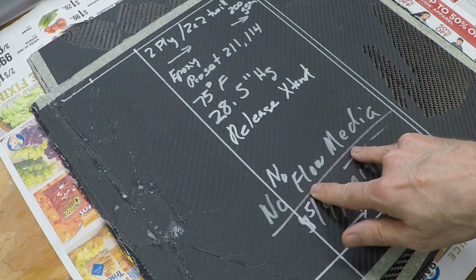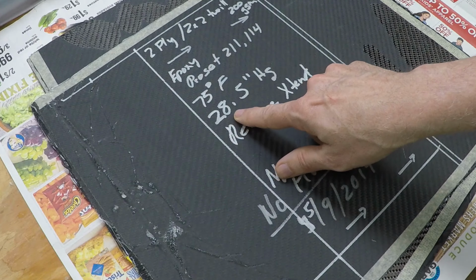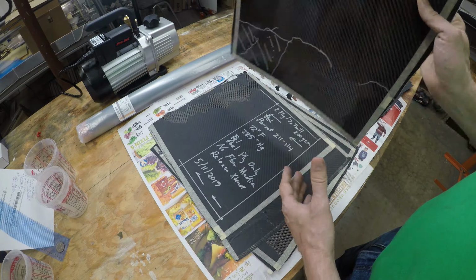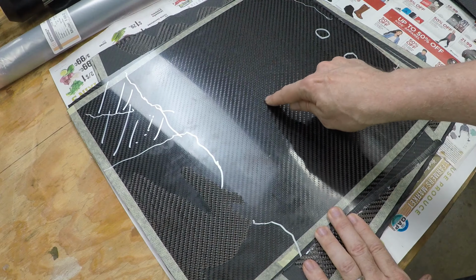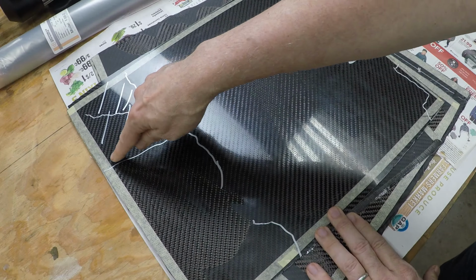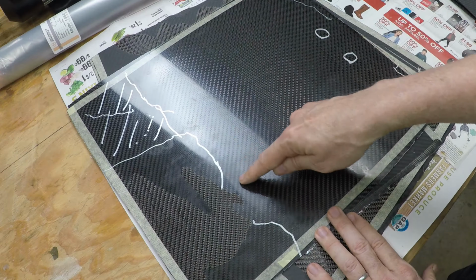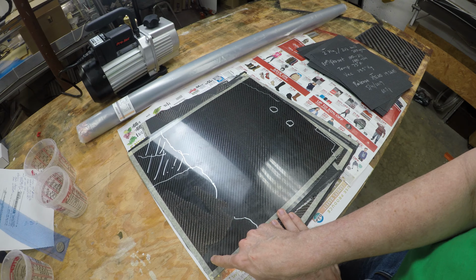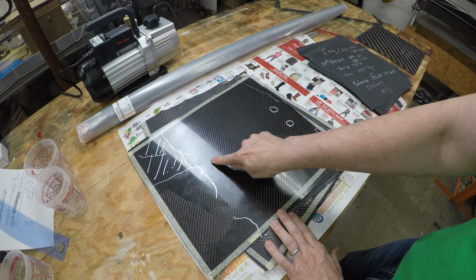And I had a comment that said, you know what, you don't need flow media and you don't even need peel ply. So I thought, well, let's give it a try. So I did a layup that only had the 2 layers of carbon fiber, peel ply, and then the vacuum bag. So there was no flow media at all. And of course I used my big vacuum pump just to make sure I had plenty of vacuum to pull through. So it flowed in from this side. It was not able to pull the resin all the way through. It only made it up to right in here. Now there's kind of 2 issues probably. One is there just wasn't enough pressure difference to make it flow through. And the other is by the time it got over here, it was starting to get a little bit thick.